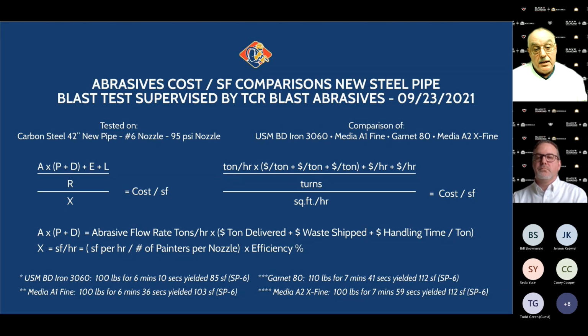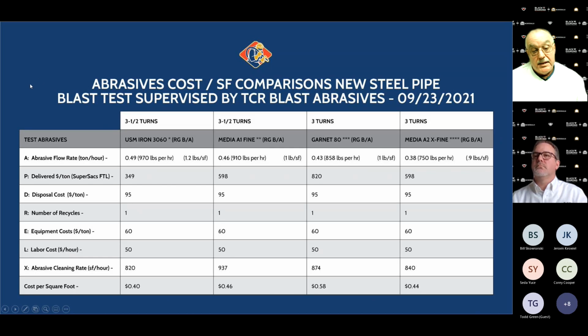And the different medias were, as we mentioned, the last video was the iron, U.S. Minerals Iron 3060, the media A1 fine, which was probably about a 40-60 kind of blend, the garnet 80, and then the A2 extra fine, which is more like a 60 by 80. So if we go to the spreadsheet, now we have something quantitative based on that test that we can use as decision makers on the abrasive, to decide which one to go with. And as mentioned, there's 3.5 turns on the first 2, the iron and the fine media, and this is on the micro valve.